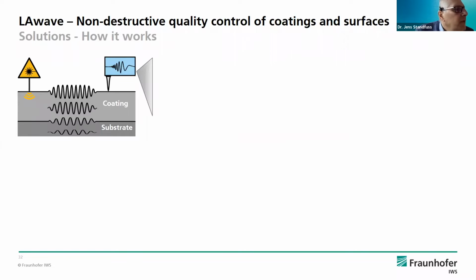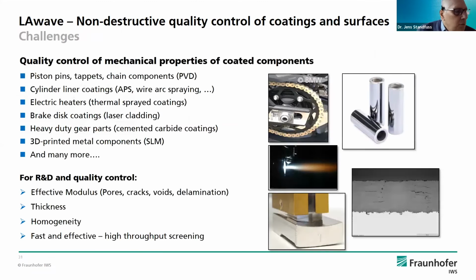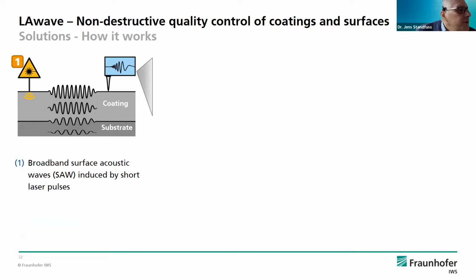How it works and what it has to do with the laser. First, you get an acoustic wave by a short laser pulse, which sends a mechanical wave through the part, and it is transmitted through the coating and through the substrate as well.